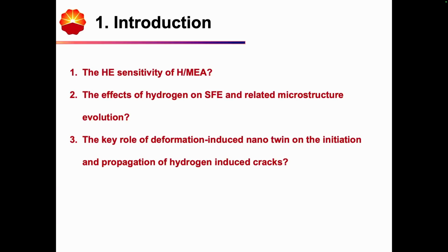Therefore, here come three questions. One is the real hydrogen embrittlement sensitivity of the Ni-Co-Cr medium entropy alloy. The second is the effect of hydrogen on the stacking fault energy and related microstructure evolution. The third is the key role of deformation-induced nanotwins on the initiation and propagation of hydrogen-induced cracks.